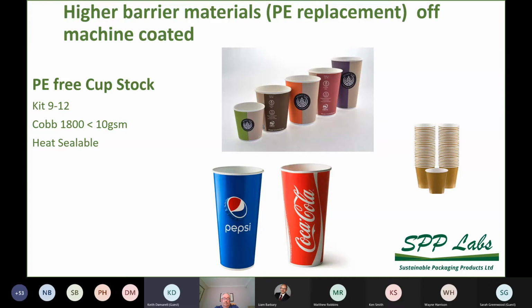The other issue is cost. The cost is also of concern, as a premium, let's say above 10% on the actual cup, could be challenging for major brands that have a very high value spend on their beverage cups. As a consequence, there has been and continues to be some general resistance by the market and the converter base, particularly slowing down transition to these materials because they are challenging to run and they are more expensive. But they are readily recyclable and compostable, and there's a steady progression away from polyethylene extruded cups to these barrier-coated cups because of their environmental position in terms of recyclability and compostability.